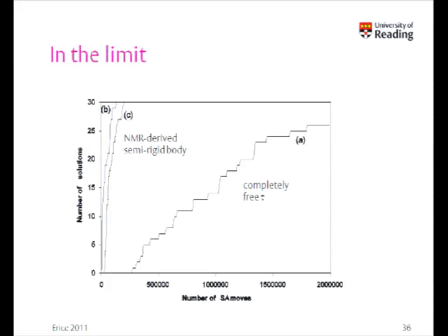And the benefit of that in terms of structure determination, these graphs won't really become clear until we've talked about global optimization. But if you imagine this as success rate against time, if we allow cimetidine to solve with all the torsion angles rotating freely, you see that it takes time to build up success. If, on the other hand, you supply a model where you've applied constraints from the NMR, then we get success in a very, very short space of time. So basically we're shifting the information balance from deficit to surplus.